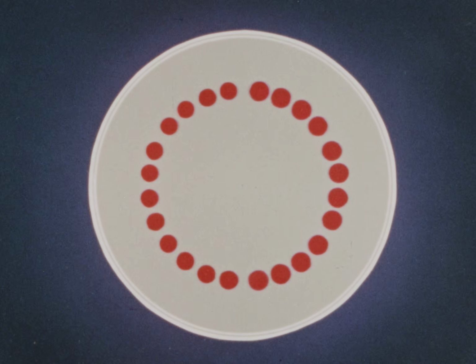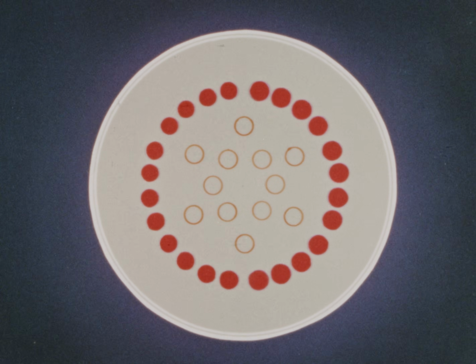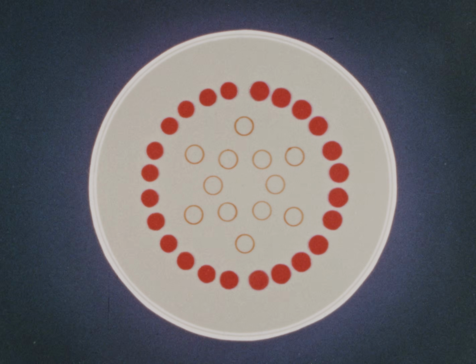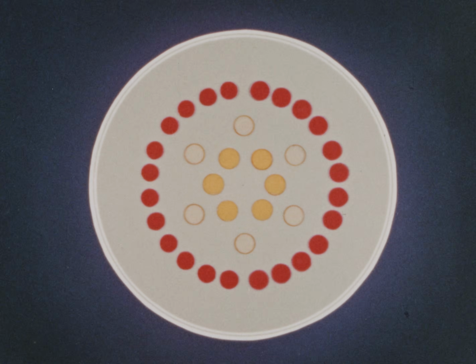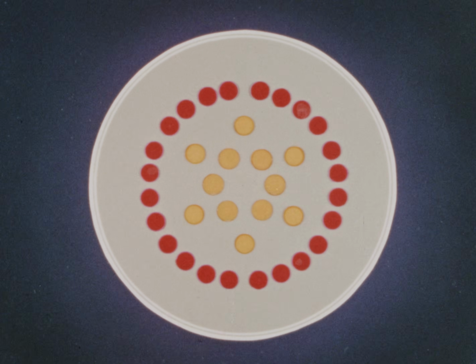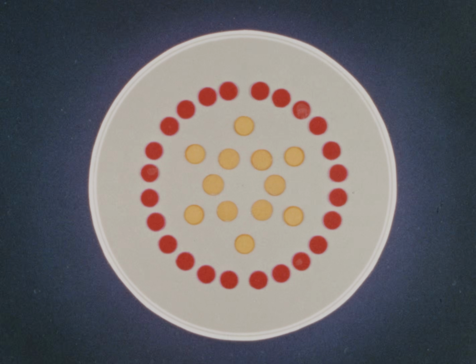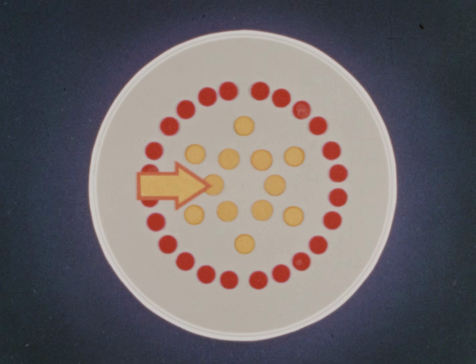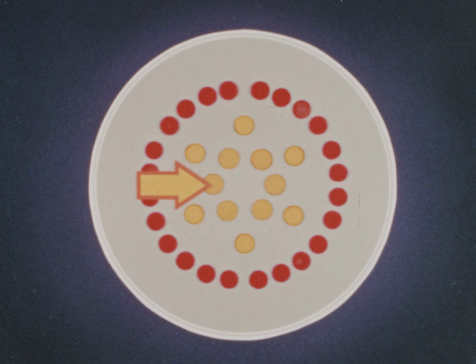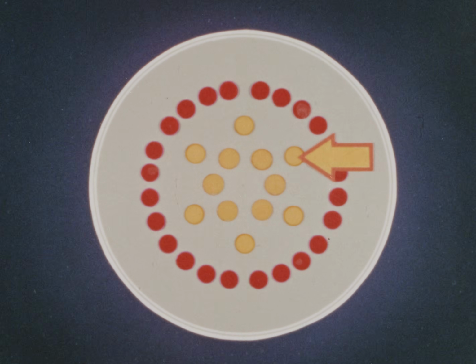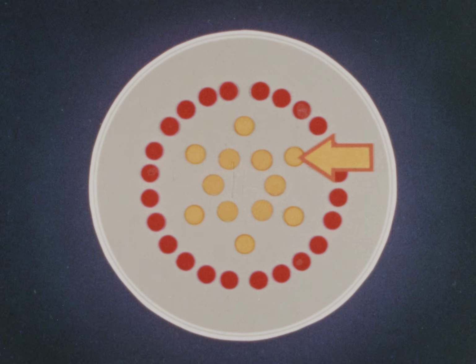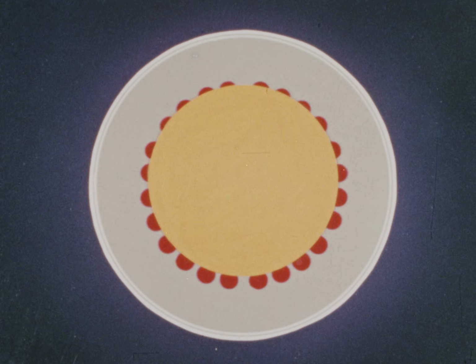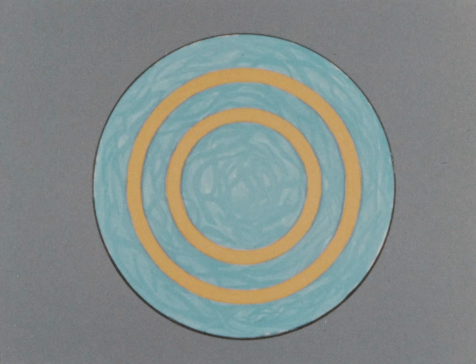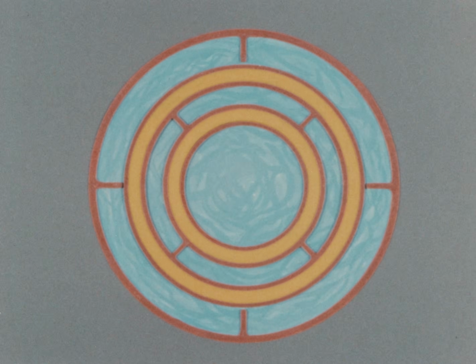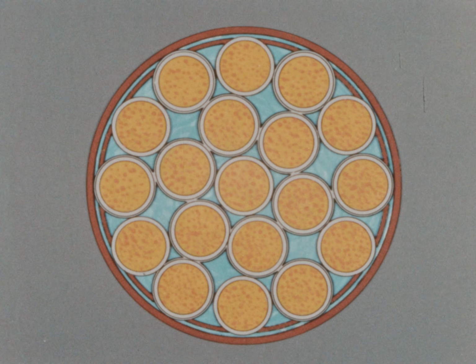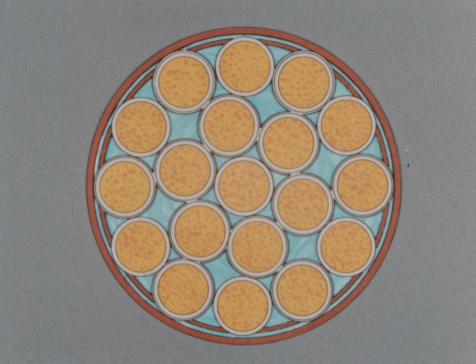The inner region of the core contains 12 test fuel positions in 2 staggered rings with 6 inner and 6 outer placings next to the driver assemblies. Inner positions will accept fuel elements of 3.5-inch diameter, and outer positions can accept up to 5-inch diameter test assemblies. Test fuel elements will be in the form of natural uranium metal or oxide tubes, or clusters of uranium oxide rods clad with zircaloy. Elements up to 10 feet in length can be accommodated.